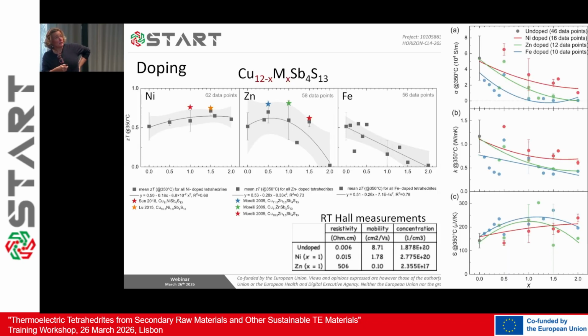With doping, again, when you try to plot, here is the ZT at 350 with the composition. Here this is the undoped, and here we replace 2 copper atoms. You see that nickel seems to be quite okay. Zinc is quite okay until 1, and then it decreases, and iron is quite bad all the time.